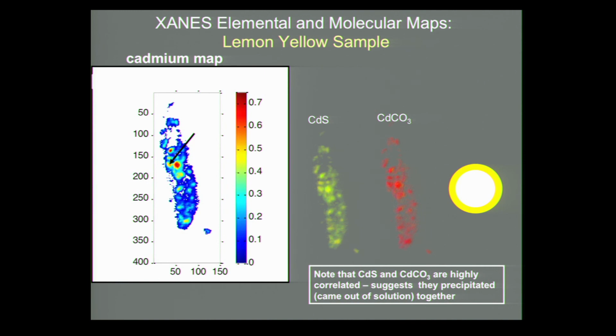There's really a one-to-one correspondence. Wherever you see cadmium sulfide, you also see cadmium carbonate. And that suggests this structure for the pigment particles.